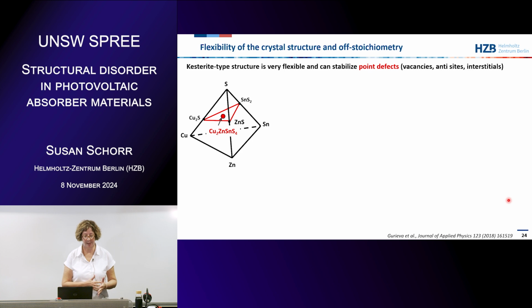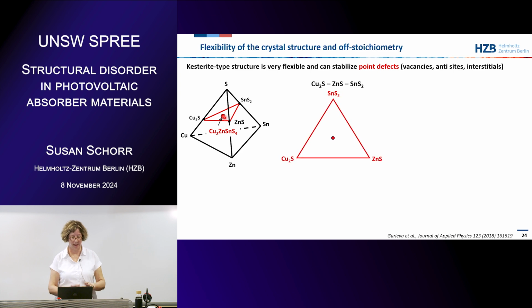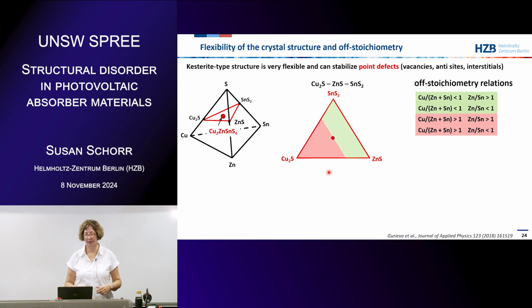So in principle, the Kesterite material can be seen in this quaternary phase diagram with copper, zinc, tin, and sulfur. You could choose this plane here with a quasi-binary diagram, and we have the copper zinc tin sulfide in the middle. If we take this triangle out, we have a copper sulfide, zinc sulfide, and tin sulfide diagram with the Kesterite in the middle. This would be the stoichiometric composition. But we know that the material can, in principle, have all these four relations with respect to the cation ratios. It can be copper poor, zinc rich, copper poor, zinc poor, and so on. This only works so nicely because the crystal structure is very, very flexible. It adopts all these point defects, so it can stabilize the point defects and the structure does not collapse.